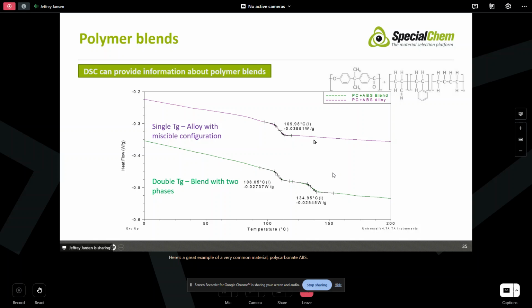If we have a single glass transition, that means that these two materials were mixed together at the ratio that gives a single phase. If those two polymers were miscible at the concentration they were mixed at, okay, single phase, one glass transition. If we see two glass transitions, one associated with the ABS, one associated with the polycarbonate segments, now we know that we've got two phases. That's not always extremely important to understand, but again, it's some more information that we can take away about our polymeric material.